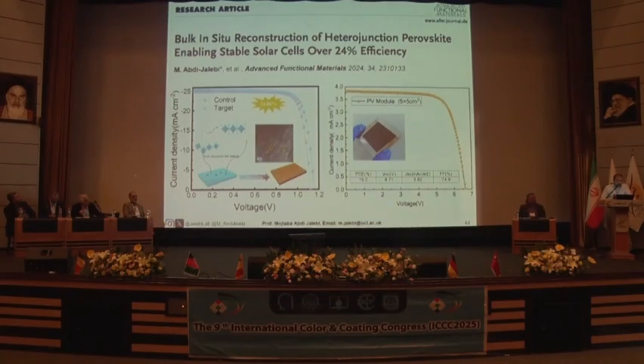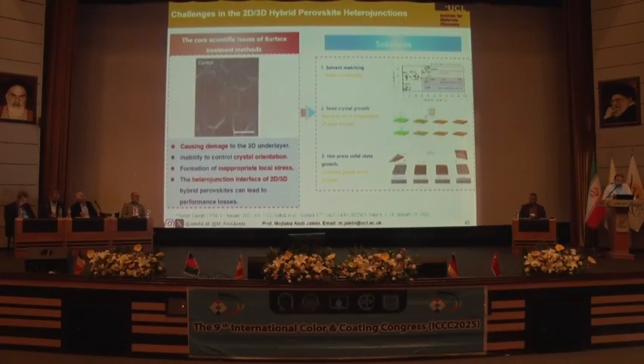Another challenge is the actual absorber material that sometimes degrades at high temperature. One of the approaches to make it stable is to utilize 2D material. You have heard about 2D materials, that they are relatively stable. And in perovskite as well, you can play with the dimensionality and make a 2D material or mix 2D and 3D. However, there are some challenges. One is solvent matching. Just to mention, a 2D phase by itself is not very optoelectronically active, so you need to have mixed 2D and 3D.